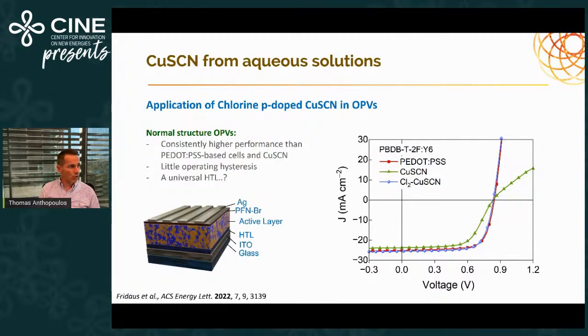Since then, and very recently, actually just a few weeks back, we published a study where we show how one can improve the electronic properties of copper thiocyanate by simple chlorine doping. Essentially, you take chlorine gas in one of the standard systems we use for etching. We introduce our copper thiocyanate layers on a substrate for a few tenths of seconds, and we see a huge doping effect emerging. The chlorine-doped copper thiocyanate exhibits much higher hole concentration, essentially eliminating a lot of the problems we have with deficiency or defects in the layer.